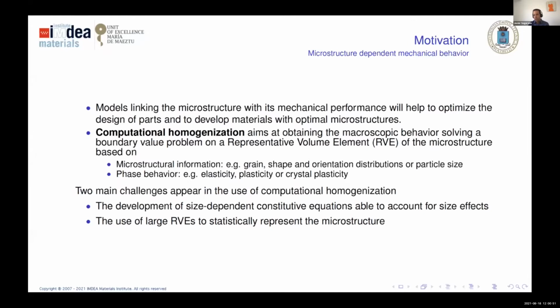So computational homogenization just aims at obtaining the macroscopic response and solving also the microfields, as has been shown by Dirk in the previous presentation, by solving the boundary value problem on an RVE of the microstructure. In this case, the results depend on the microstructure and the behavior of the phases. That can be anything from elasticity to crystal plasticity or damage models.